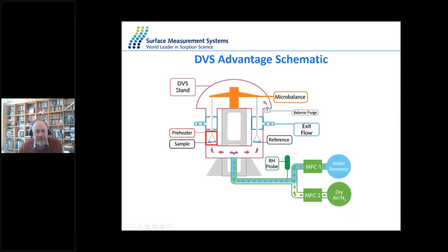So basically, this is a thermogravimetric technique. So the first thing is that it has a microbalance. This microbalance can measure very small mass changes, and we will resolve 0.1 microgram. So even if we've got a 10 milligram sample, we can actually measure one part in 100,000 in terms of mass changes. So the small sample will go here, and typically it's 10 to 50 milligrams, can be smaller if you want. And this is all maintained inside a constant temperature thermal environment.